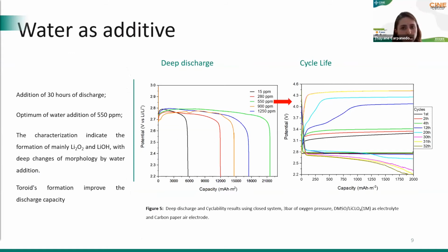And using the optimal conditions, so closed operation, using 3 bar of pressure, and DMSO as solvent with lithium perchlorate, and only the carbon paper substrate as air electrode, we verified that the addition of water, especially 550 ppm of water, allows 30 hours more of discharge. So we verified an optimization adding this amount of water in a systematic study that we are concluding, and it is indicating that this is really correlated with the morphology of the product.